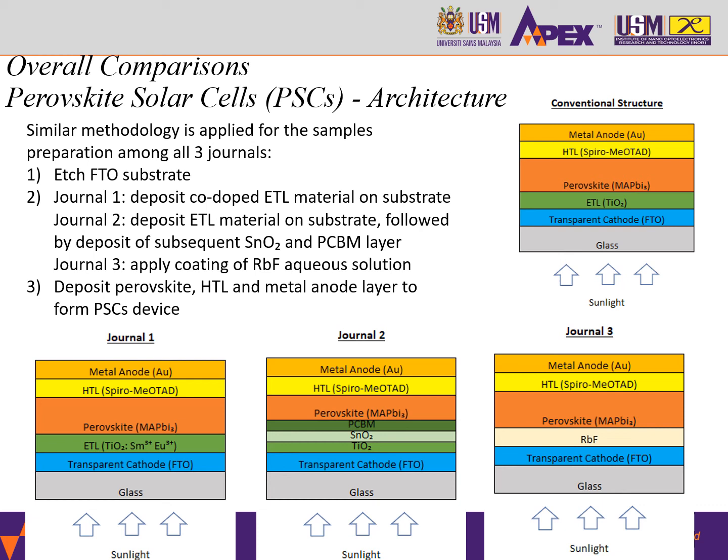All three journals go through a similar preparation and methodology, whereby they have to etch the FTO substrate, followed by the deposition of the ETL material, and then lastly the deposition of the perovskite layer, HTL, and also the metal anode layer to form the final PSC device.